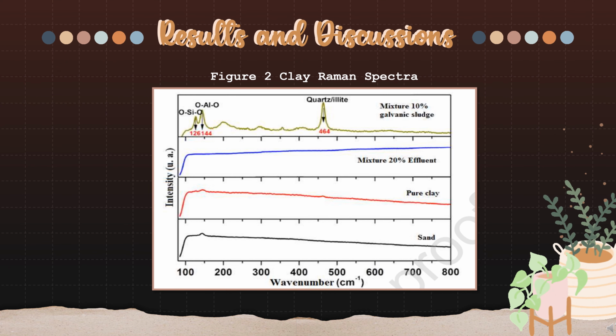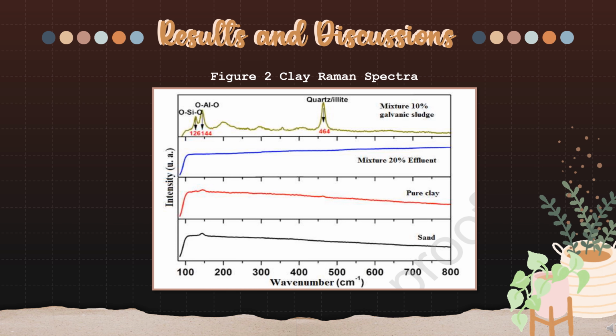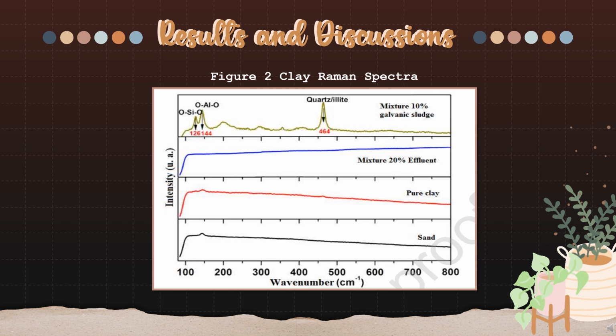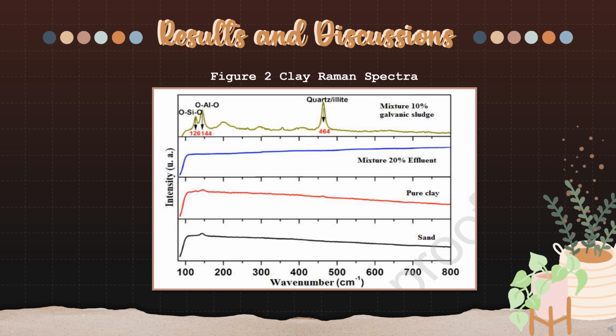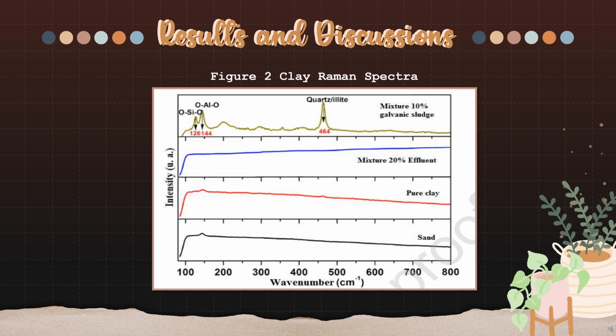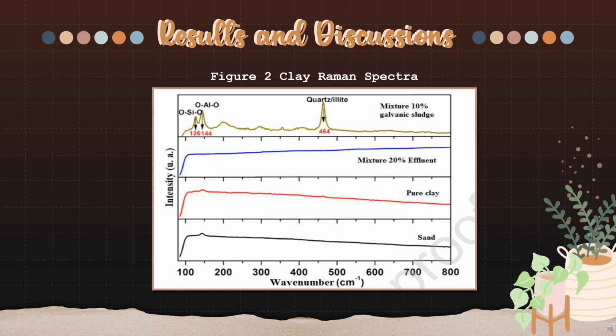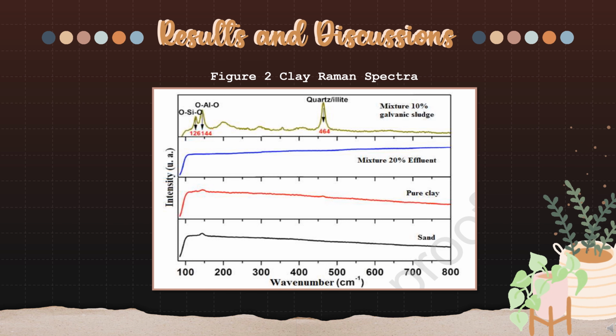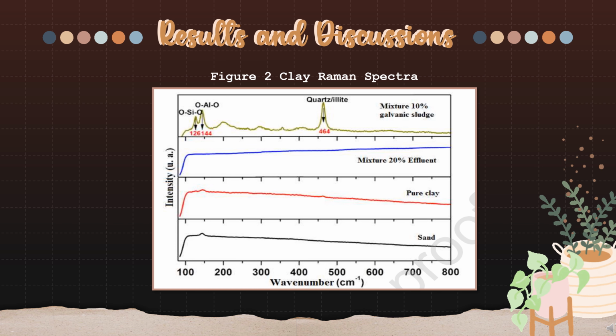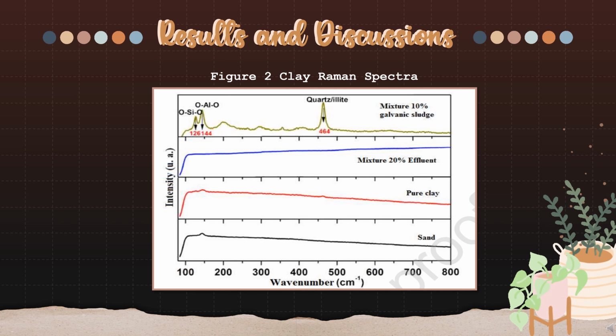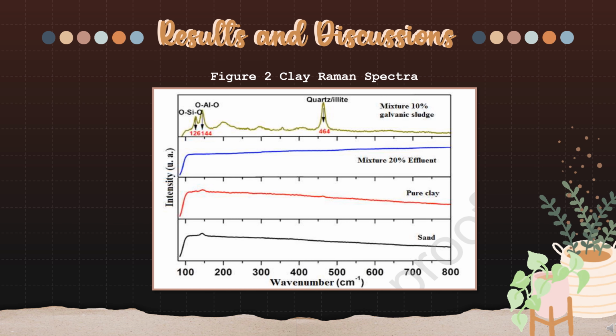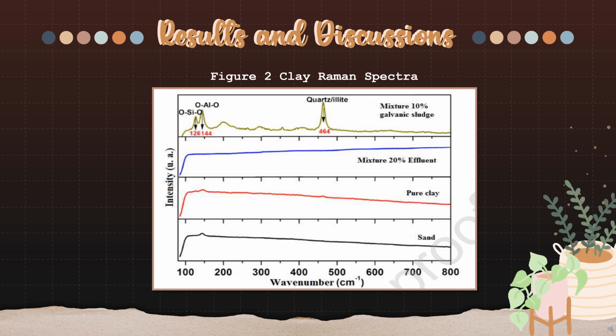Figure 2 illustrates the clay spectra analyzed by Raman spectroscopy, and it shows bands at 464, 144, and 126 per centimeter that reflect modes associated with deflection of the silicon-oxygen-silicon bond in quartz or illite, oxygen-aluminum-oxygen bond, and silicon-oxygen-silicon bond, which are all associated with symmetrical folding, respectively.